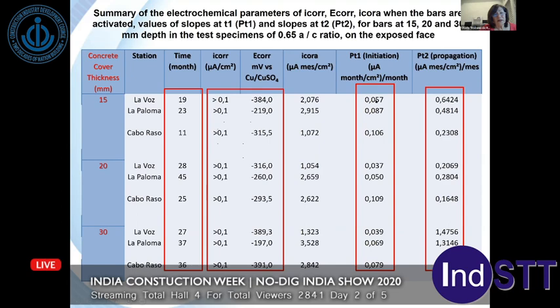Next figure shows the behavior of the other marine environment, where you can observe the difference between the other marine environment and this one that are activated. Note the slope, which is similar to the behavior of the rebar in La Voz, Cabo Raso, and La Paloma during the initiation period before rebar activation.